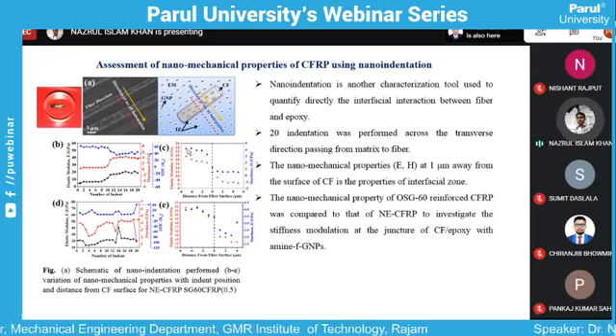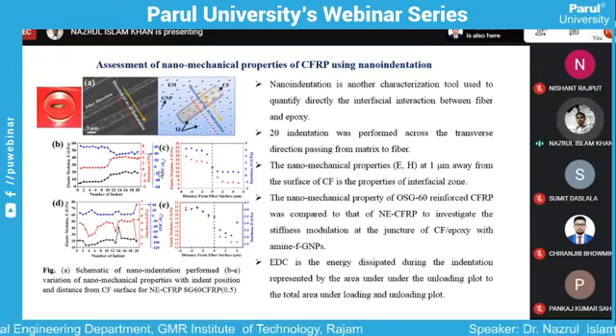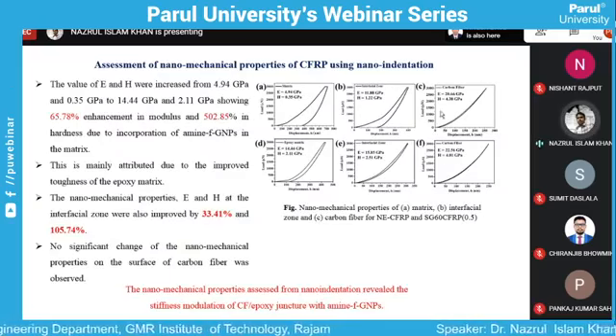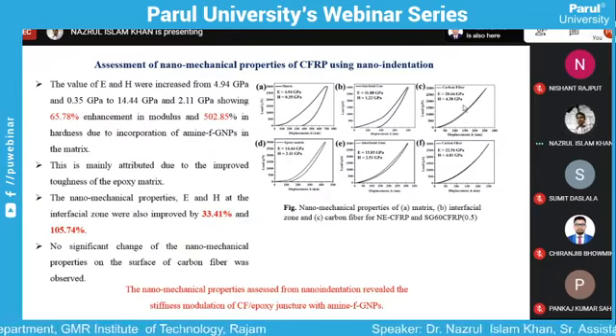Along this interfacial zone, if you see the neat epoxy, without any modification or surface functionalization of graphene, the interfacial properties are low as compared to when it is functionalized. This is without any graphene, and this is with graphene.